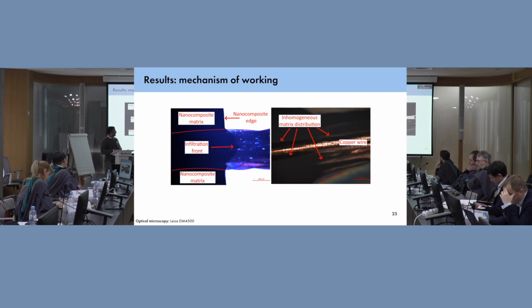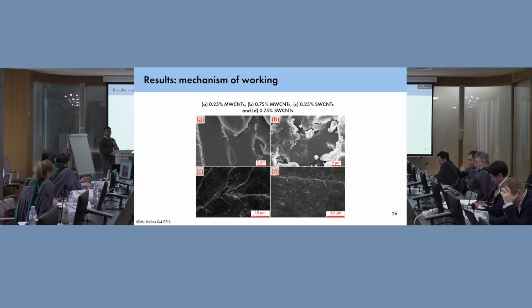So we also took a look at our traditional metallic embedded electrodes, and we see that, okay, microcracks are present, but there's no real infiltration. There is inhomogeneous distribution, which we did not see along the length of this one, and there is separation. In some places, we also see just epoxy without any visible agglomeration or CNTs that we could discern from optical microscope. So of course, we needed to take a look at this in a bit more detail, and we went